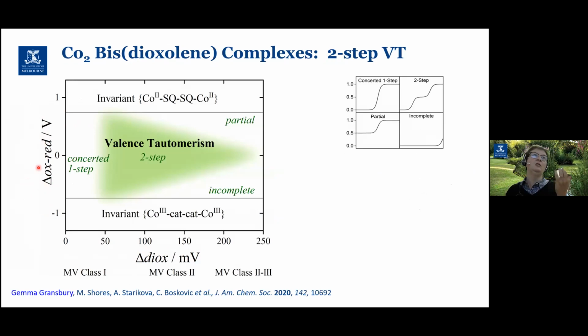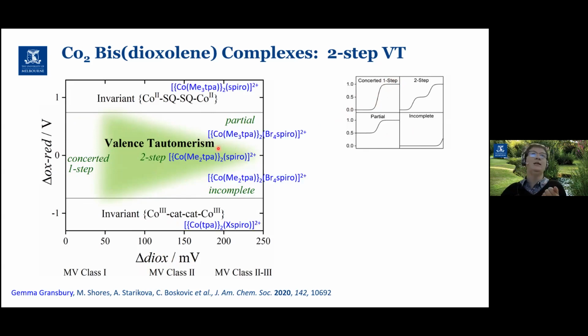So if delta ox minus red is too large, either positive or negative, we're stuck in either one homovalent form or the other, so the cobalt-2 semiquinone or the cobalt-3 catechol. So that's not what we want. So it's only when the delta ox minus red is at a smaller value, those processes are close together, and that's when delta diox comes into play. So if delta diox is too small, the communication is too small, we just see the concerted one-step transition. If the communication is too great, instead we see the partial or the incomplete transitions. So it's only in this sort of intermediate spot where we can see that two-step transition.